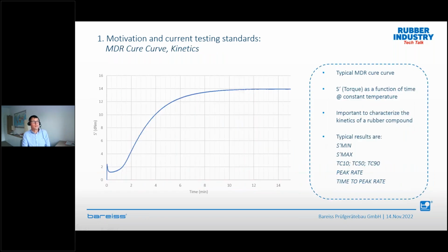So if we do another standard test, this is our MDR curve, which is a very, very important measurement in the rubber industry. So we need this, for example, here, the S prime as a function of time. That is a very important measurement to characterize the kinetics of a rubber compound. There is no doubt of this. That is something we need, and we need typical results like the minimum of a curve, the maximum of the curve, the conversion rates, like the conversion of 10%, 50%, 90%, and so on. We can calculate a lot of values on an MDR curve.